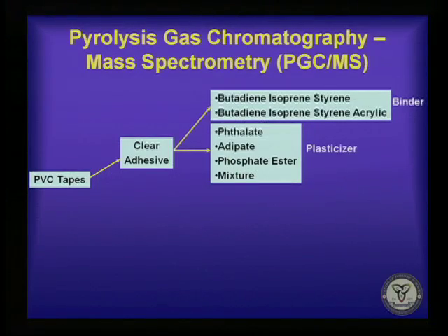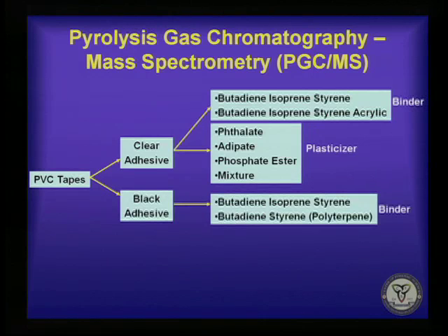Using PGC-MS, for the clear adhesives, we saw that we had butadiene isoprene styrene, and we also saw small amounts of an acrylic component, which we did not see by IR. And it gave us more information about the plasticizers that were present, namely the minor components that we weren't always able to see by IR. For the black adhesives, we were able to determine what those were, butadiene isoprene styrene and butadiene styrene with a polyterpene tackifier. And the plasticizers, again, it gave us more information about the minor components that were present with the adipates.